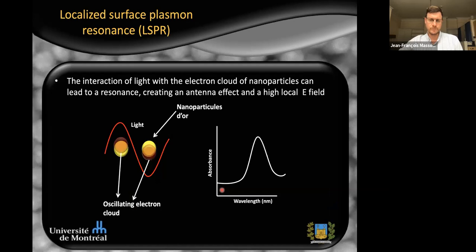We base this on the optical technique of plasmonics. Plasmonics works on metallic nanosubstrates — in our case, often gold nanoparticles smaller than the wavelength of light. When light comes in, the electric field will attract or repel free electrons in the particle, and due to the oscillating nature of light, these electrons come into resonance and oscillate at the same frequency, creating an absorption band in a UV-Vis spectrum. This can be used for building chemical sensors; we've done many refractometry-based sensors where the position of the absorption maximum changes depending on which molecules bind on the particle surface, allowing detection of specific molecules.